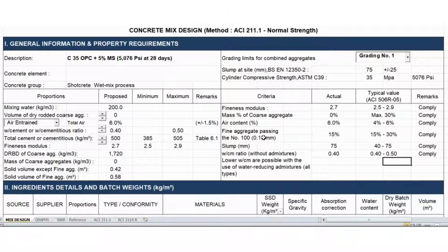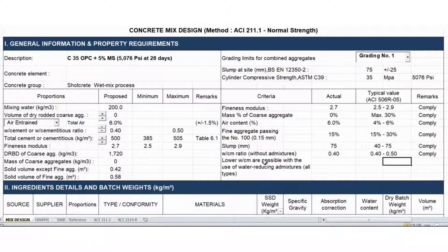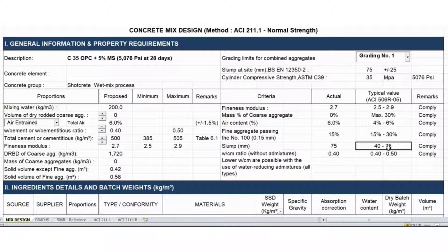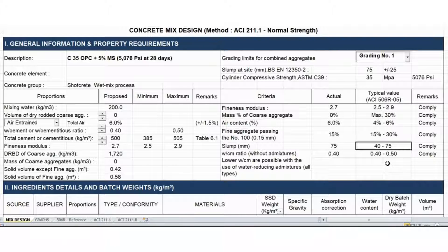For the fine aggregate grading, fine aggregate passing number 100 is between 15 to 30 percent. The slump value is 40 to 75 mm and the water-cement ratio between 0.4 to 0.5. A quick recommendation on slump: you can ask your applicator or subcontractor which slump value they are comfortable with, depending on the equipment.